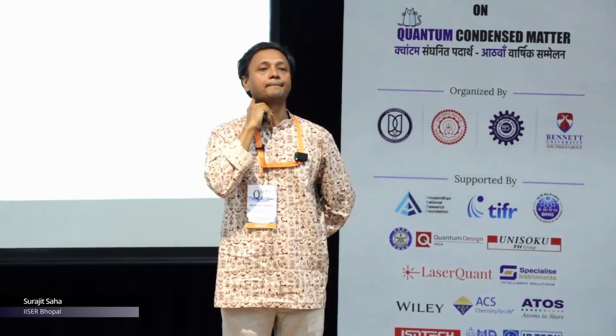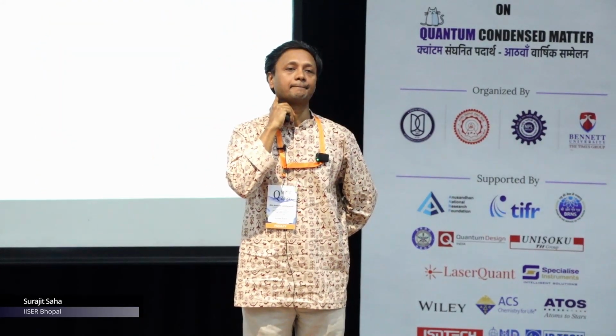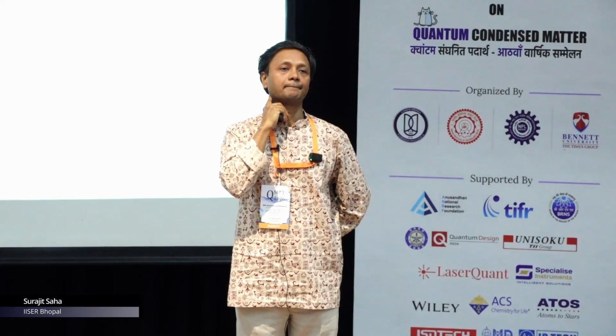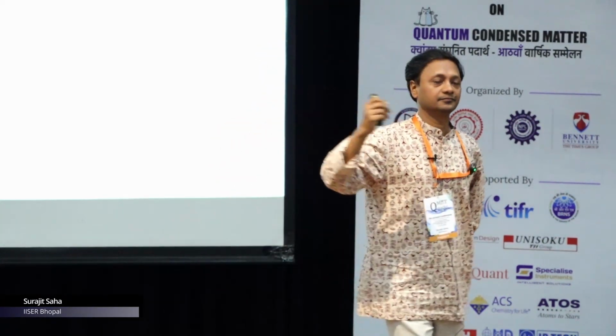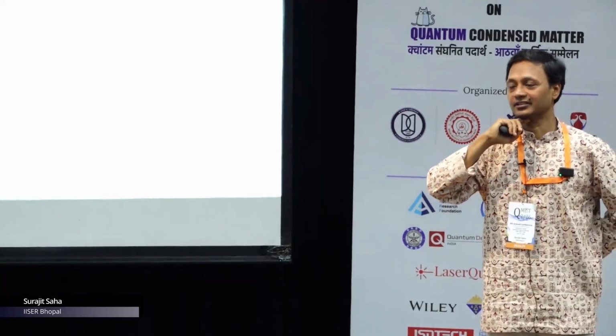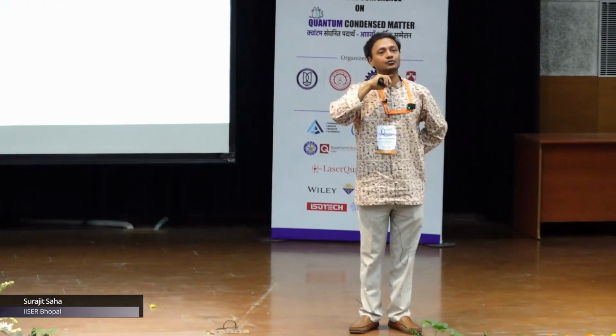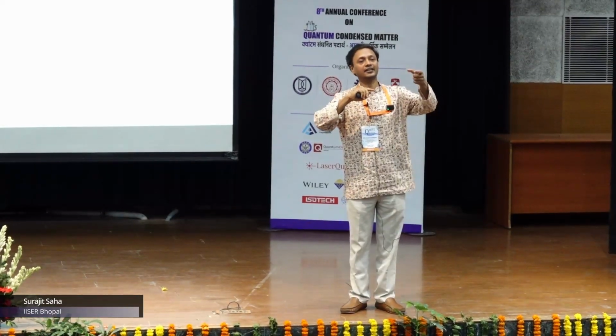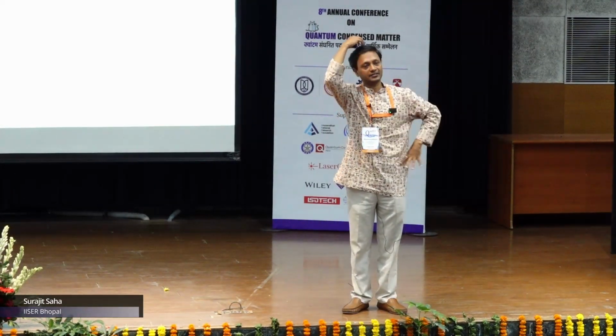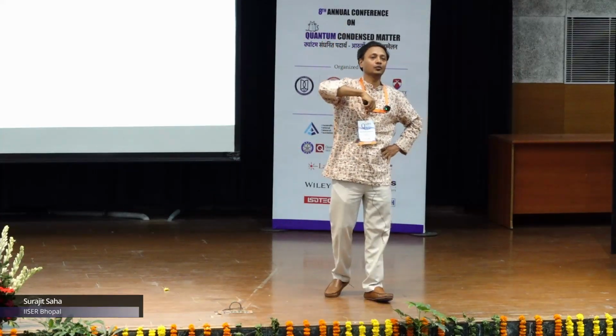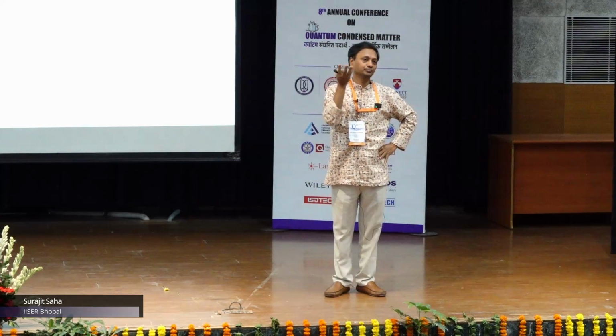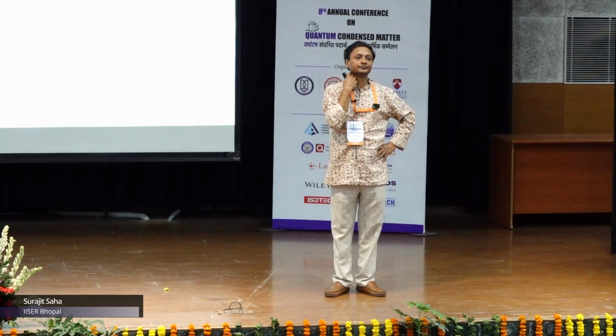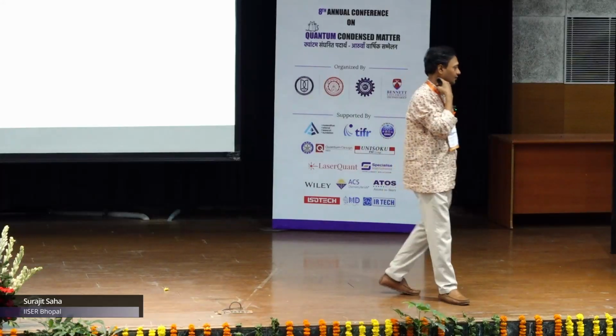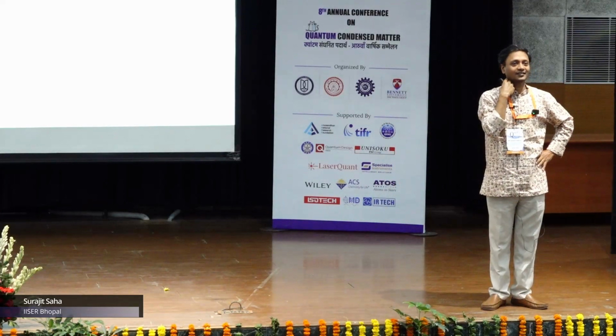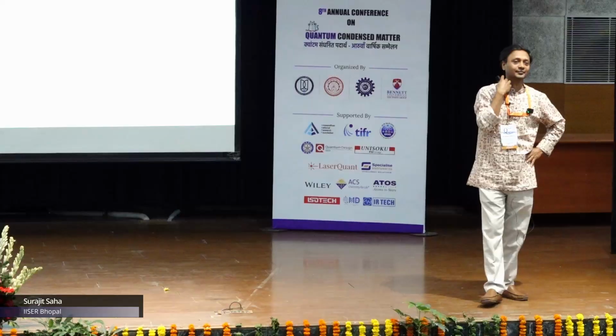Just two quick questions. Very nice talk. Could you verify the structural transition with some other experimental probe, like diffraction or something? As I was responding to Vaiti's question, we actually tried to do X-ray diffraction. The point was our flakes were so small that the routine X-ray diffractometer will not be a good way to do it. So we'll have to figure out a better way. I see. The next was that you saw some wrinkling. Do you see any signature of flexoelectricity, like coupling to the strain gradient? One has to measure it. I believe there should be.